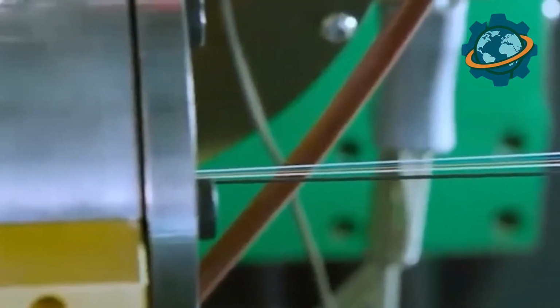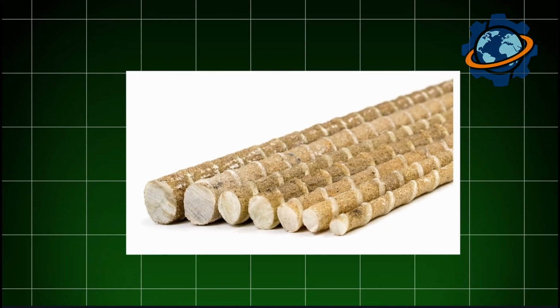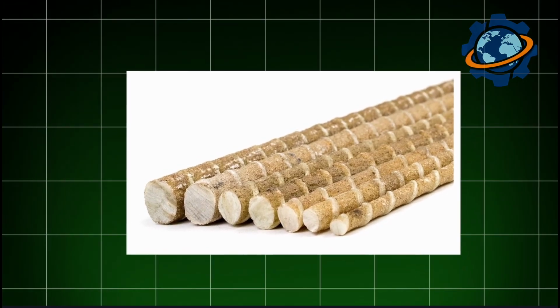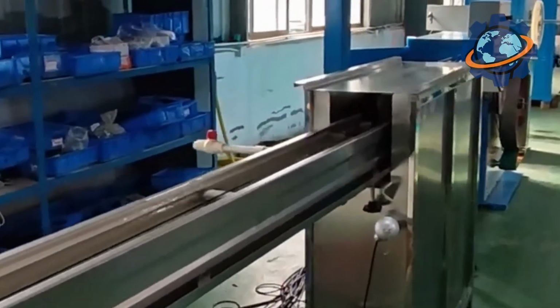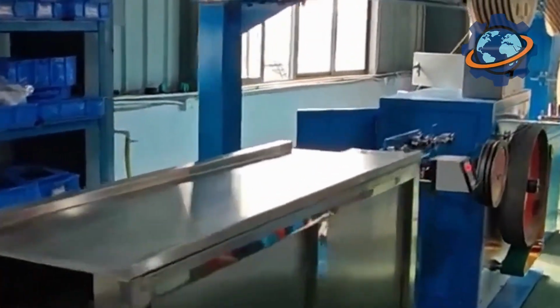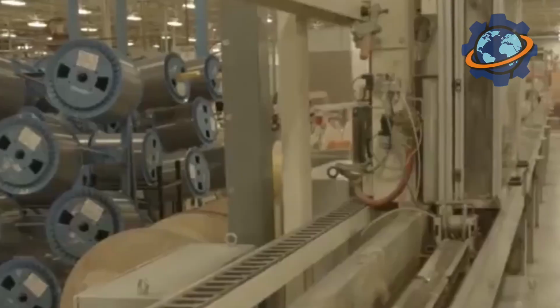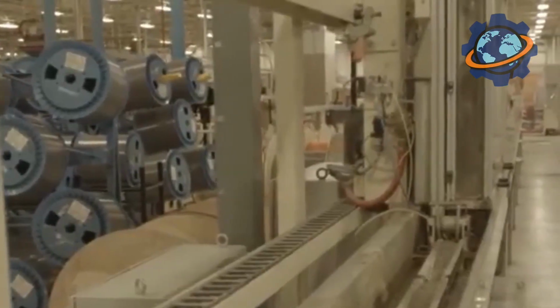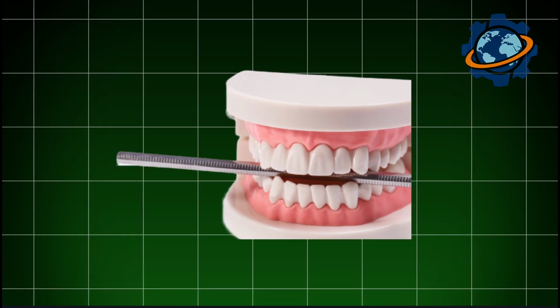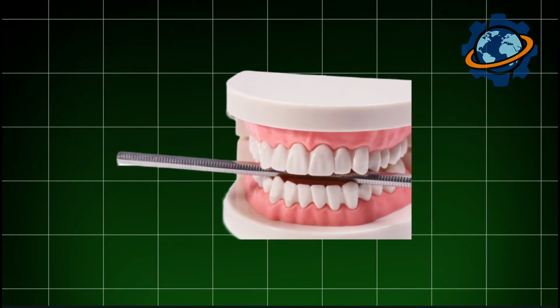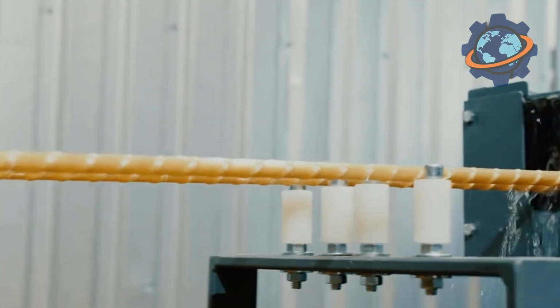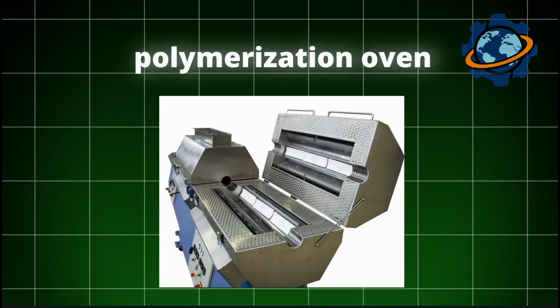Immediately after exiting the die, while the rod is still hot and soft, a special strand of the same fiberglass is wound around it. A thin, resin-saturated thread is wound in a spiral on the surface of the rod, creating a relief pattern. Sometimes, for even better adhesion, fine quartz sand is sprinkled onto the sticky surface, which adheres permanently to the resin. Now, our rebar has not only strength, but also teeth with which it will hold onto the concrete. The formed and wrapped rod enters the longest part of the machine, the curing tunnel or polymerization oven.